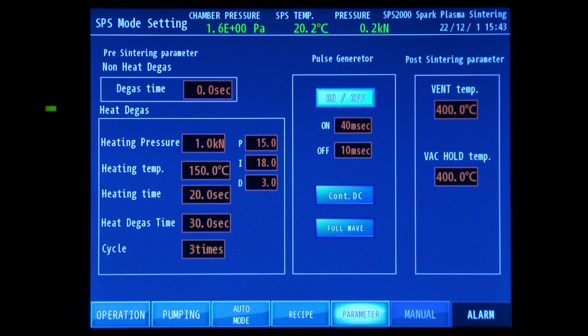First of all, we have a pressure that we apply to use the degassing function. This is a very low force, just 1 kilonewton on a 15 millimeter die, not to compact it too much. We have also selected the heating temperature, so we'll heat the sample up to 150 degrees. We keep it there for 20 seconds, and then we lower the sample again, and we let it vent for 30 seconds. And we can repeat this 3 times here. Of course, all of these parameters can be changed. In this window, we also have the PID settings for this regulation.